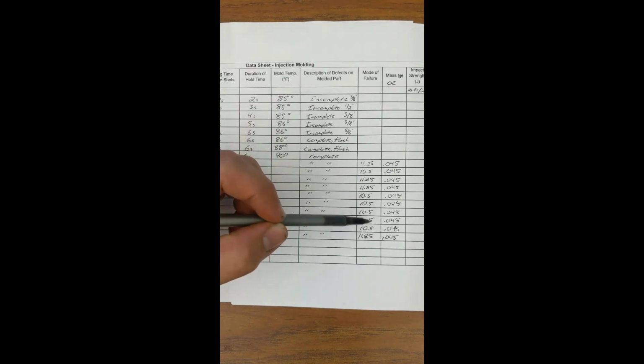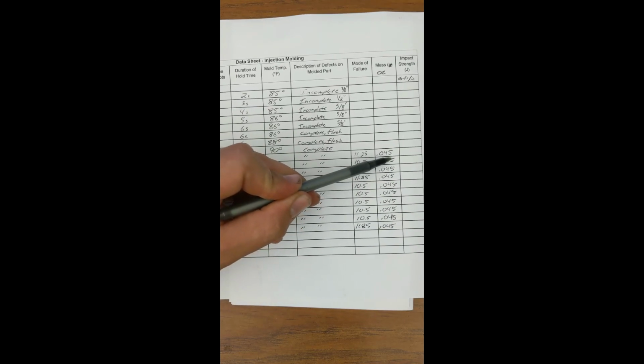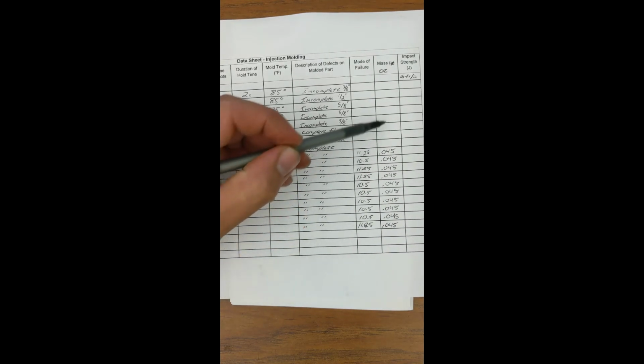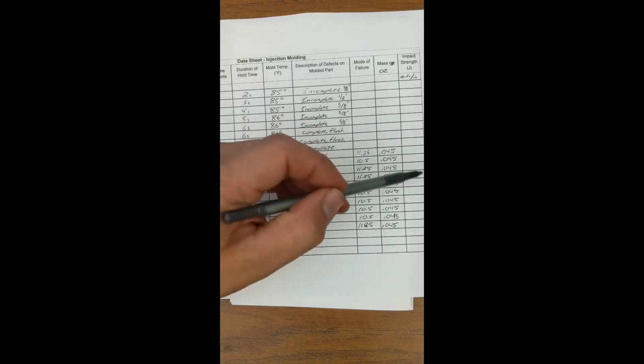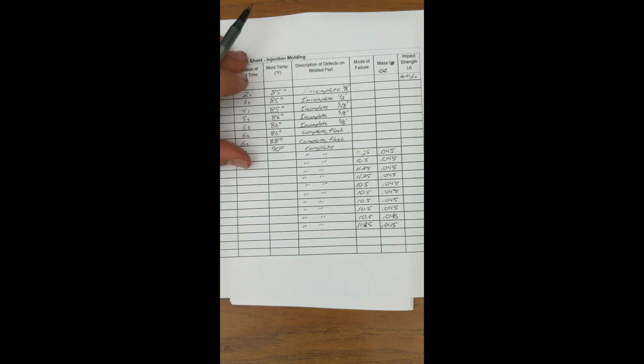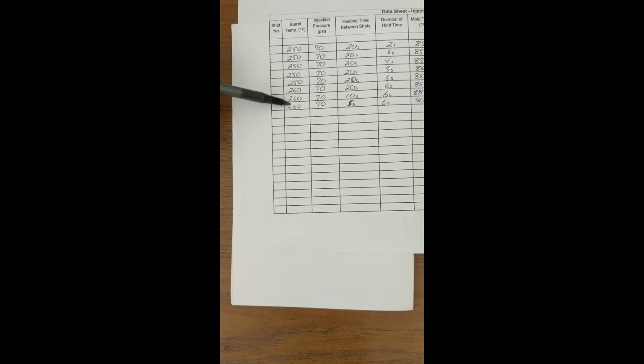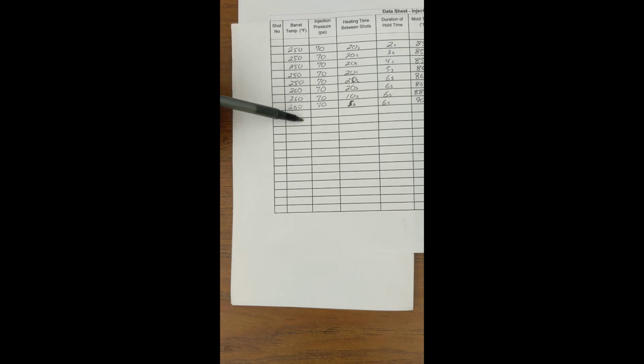In order to wrap up this week's activity, now that we've gathered some data, we've got a little bit of math to do. I want to share with you my data sheet. And on my data sheet we have our masses for our golf tees. I accidentally put the impact strength over here and the mode of failure column, but that's okay. You can still use these numbers to help evaluate what type of plastic. The first thing you're going to look at is right here in barrel temp, the process temperatures. You're going to be looking for a plastic that has a melt temperature around this range, around 250, especially 260 degrees Fahrenheit. So that'll be one clue.